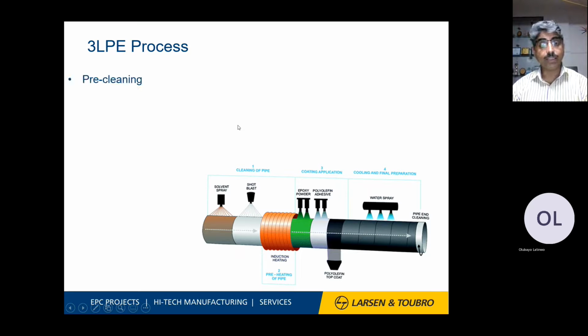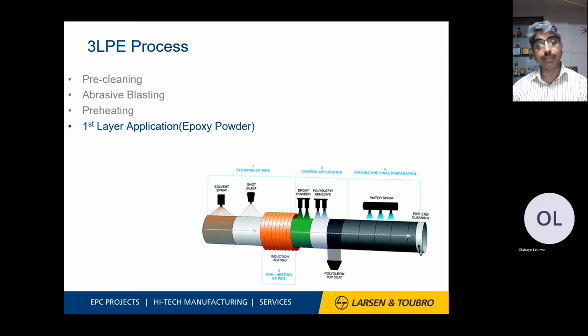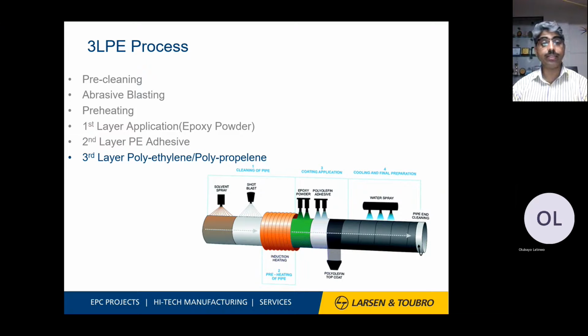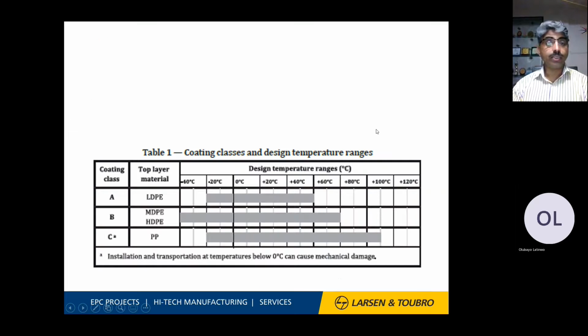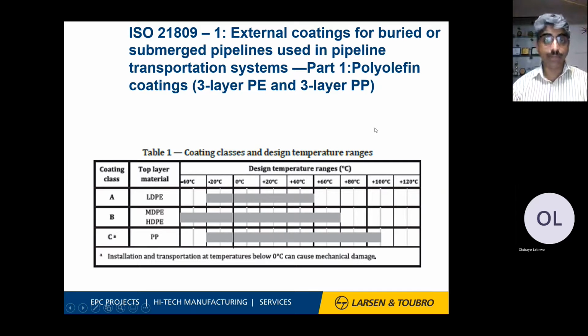Coming to the 3LPE process, normally pre-cleaning, then abrasive blasting, then preheating, then the first layer application of epoxy powder, then the second layer of polyethylene adhesive, and the third layer of polyethylene or polypropylene, by which you close this process. The only limitation is that it is applied only in the shop, not in the field. And you have to do cooling, of course, because it is a hot process. At the end, you cool so that the coating settles over the pipe and gives good adhesion properties. So this is all about 3LPE and 3LPP.